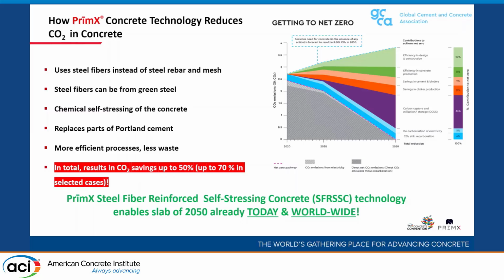We use chemically self-stressing concrete. We can replace quite substantially parts of the Portland clinker. And of course, as we reduce the thickness and we make large daily castings, this process is very effective. That also contributes to CO2 savings. So in the end, we can save up to 50%, in some selected cases even more.